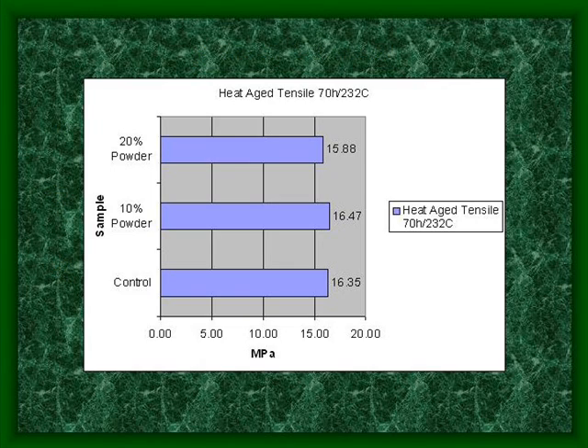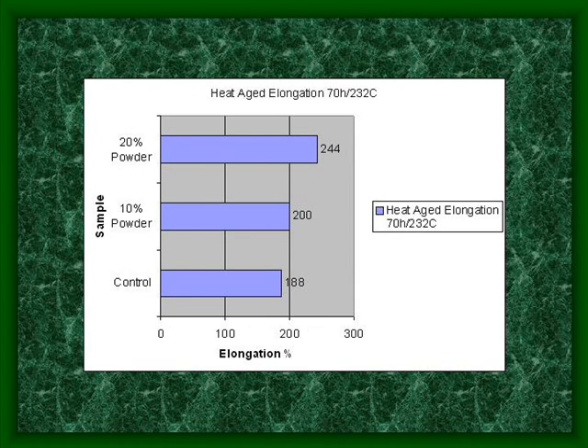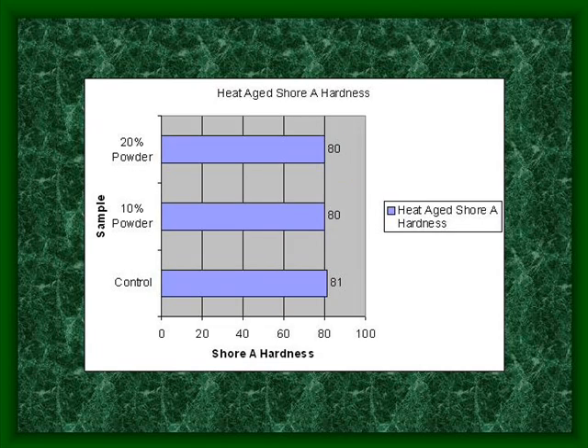This is heat-aged tensile strength, 70 hours at 232 C. All of the samples were equal under this test. Heat-aged elongation was actually higher for the two samples that contained the micropowder. Heat-aged hardnesses were within 1 point.